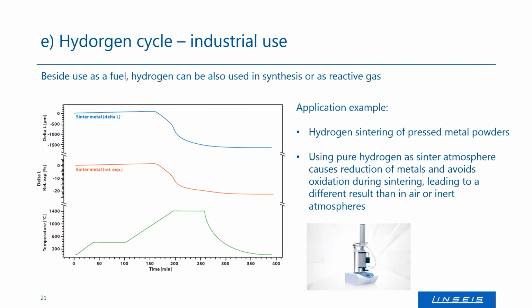Because during the sinter process, what you usually have is metals and metal oxides, and if you burn them in air, they will form an alloy, but they will sometimes also form alloy with oxides. And especially if you have sinter metals or special ceramics for industrial use, the oxides are not wanted. You want to have a pure metal structure, and therefore usually the oxygen is removed by the hydrogen atmosphere. So if you fire them in hydrogen atmosphere, you get a different result than firing them in air. And that's just also some example where we are already involved. So hydrogen sintering is something we typically do.